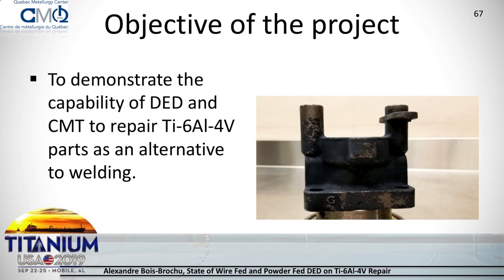So the first objective of this project was to demonstrate the capability of DED and CMT to repair TI64 parts as an alternative to traditional welding, which, because it induces a lot more heat, tends to induce distortion into fairly small parts. So when you want to work on repairs on small sections of parts, DED is much preferable because of the decreased distortion as a result, and usually increase in mechanical properties.